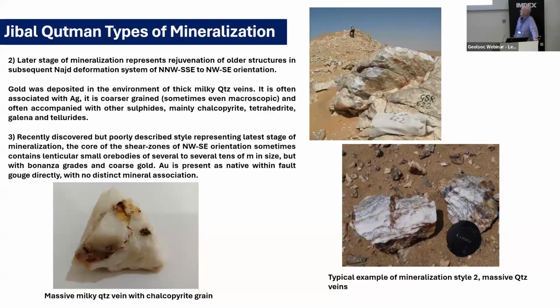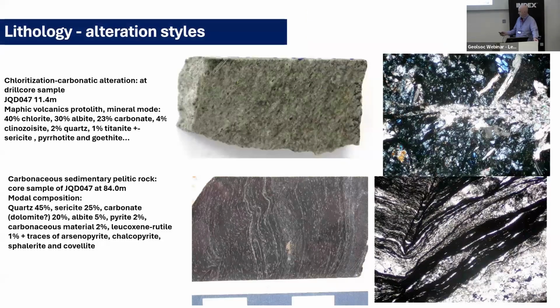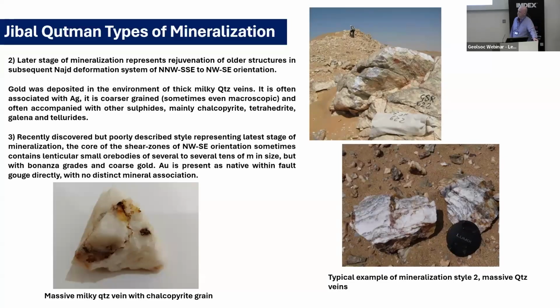This all looks really sweet. The quartz veins are generally high grade. There is a lot of disseminated mineralisation of lower grade. The average grade of the deposit is around about 0.7 of a gram. Because of the price of gold doing what it's doing, the grade is now down to about 0.65 of a gram. So if you start talking about sulfides, especially complex sulfides at 0.6 of a gram, then you have to be pretty clever how you're going to make money out of that. So again, going back to just the chemistry of the deposit, you really need to take into account mineralogy.